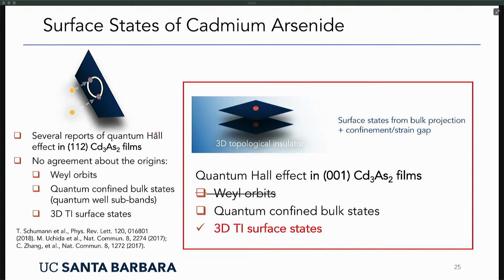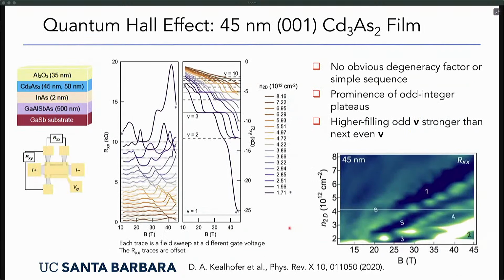To sort this out, it's easier to go to the 001 cadmium arsenide surface, where we should not have any of these Fermi arc states, which immediately rules out any Weyl orbits. So the two remaining possibilities for the origin of the quantum Hall effect in these thin films are quantum confined bulk states or 3D topological surface states. I will show you that the last one is the correct interpretation by doing two different kinds of experiments.